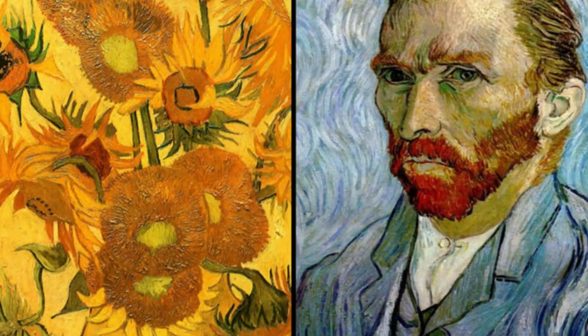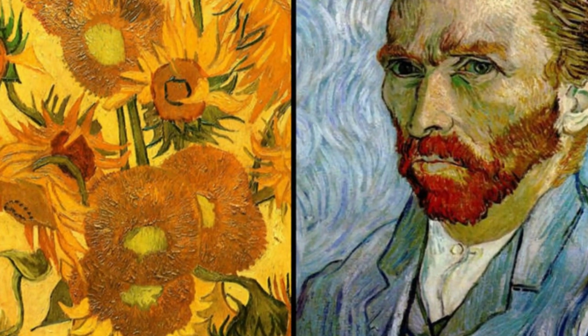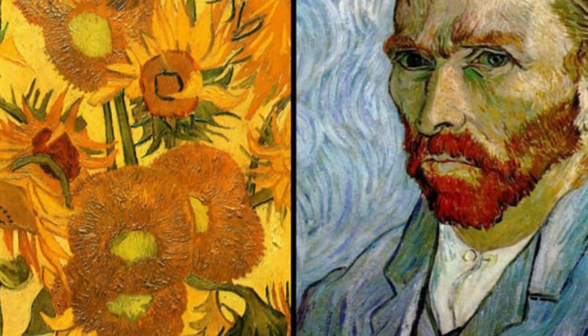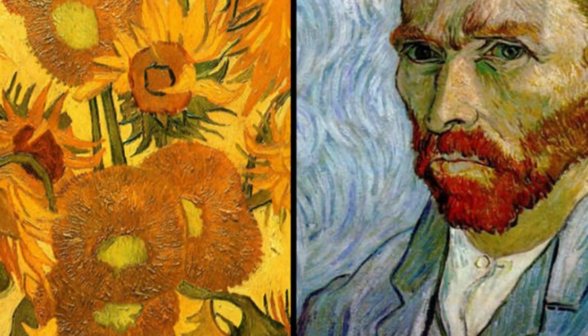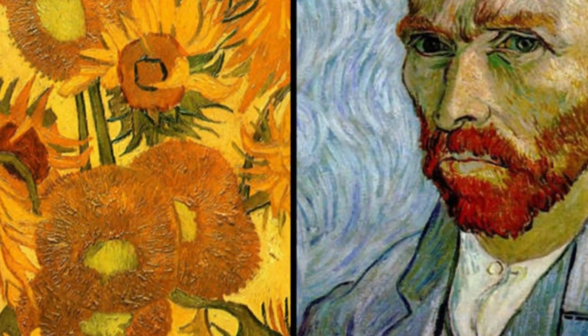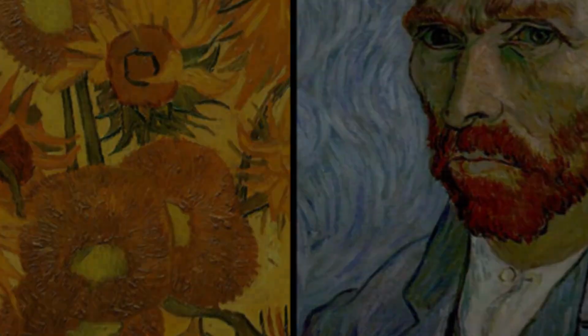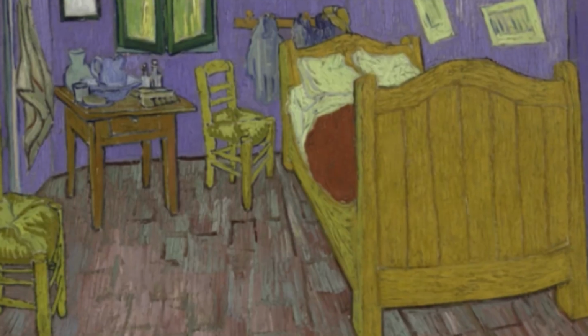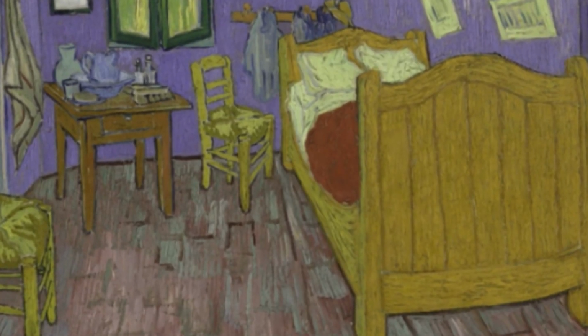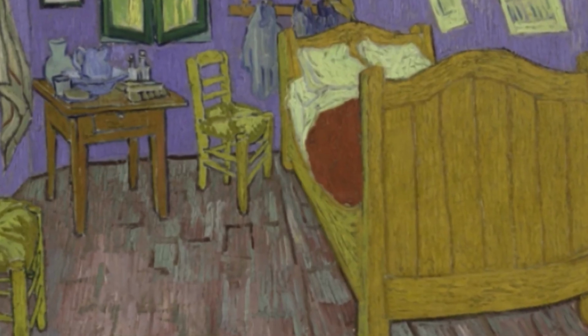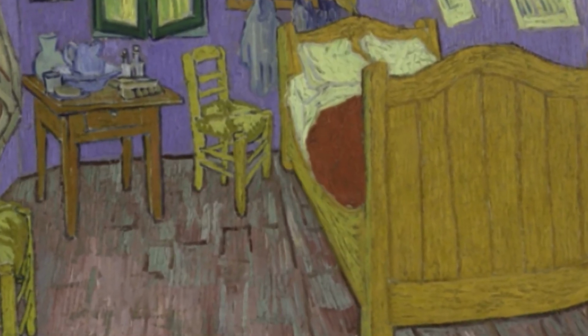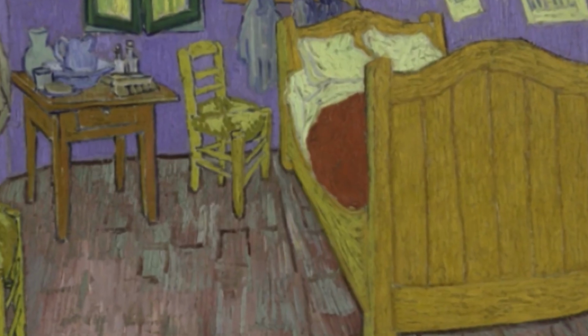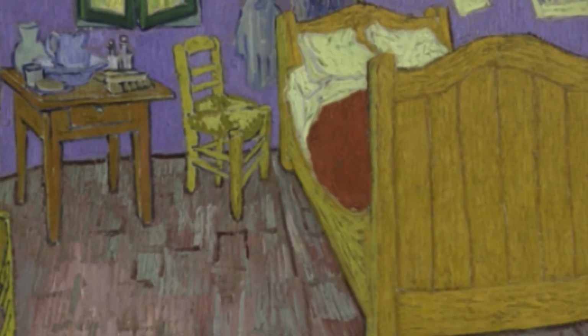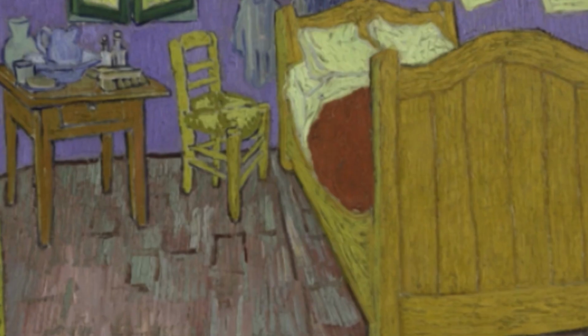The darkening of yellow tones is a direct consequence of changes in the state of chromium in the pigment. Moreover, the process occurs unevenly across the entire surface, but locally, where the pigment is closer to the surface and receives more light. This means that what we see in museums today, the Sunflowers in London's National Gallery, the Bedroom in the Musée d'Orsay, are not what the artist himself saw. They are versions of his paintings, altered by the chemistry of a single element.